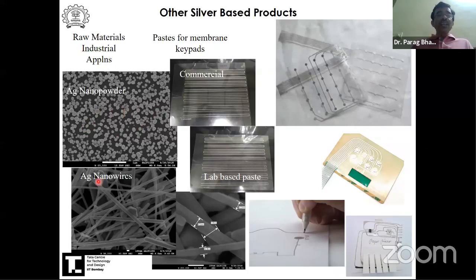And then we also made silver nanowires. This small tiny white bar that you are seeing is 100 nanometer. So you can see the diameter of this wire is like 100 nanometer, which is like if you take our hair and split it maybe 1,000 times or even more, then you will get this size. So these are so small wires that we make of silver. And it has very interesting applications. If you coat these silver nanowires, for example, on glasses, it will keep the glass transparent, but the glass will become conducting. And then there are many applications for making devices.